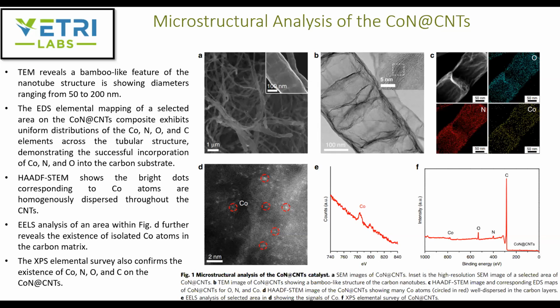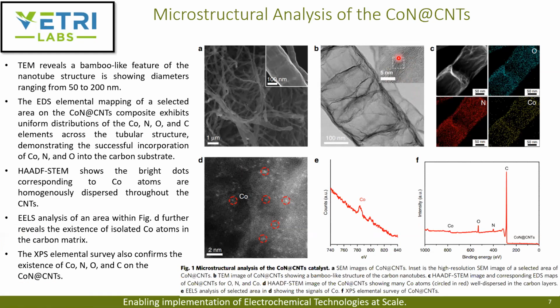First, let's look at their microstructural analysis. As we see here in the SEM, they were able to find carbon nanotubes, and with the help of TEM, they could see a bamboo-like feature resembling the CNT backbones, with diameters ranging anywhere between 50 to 200 nanometers. In the inset, you can see the lattice fringes, about 0.35 to 0.36 nanometer, indicating the 002 graphitic plane, because in a densely packed graphitic structure you have about 0.34 nanometers. So this increase tells us that it could have been expanded due to the doping of cobalt and nitrogen.